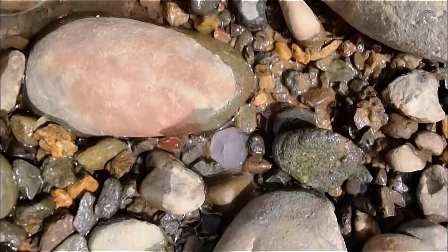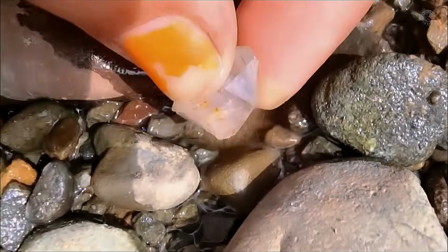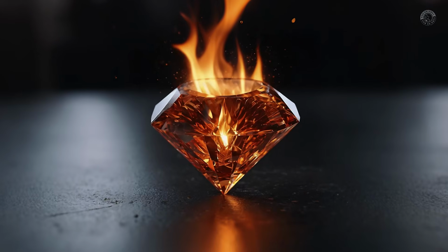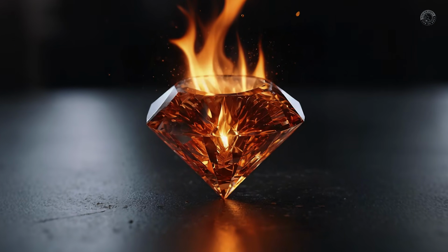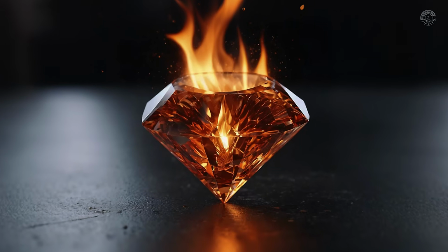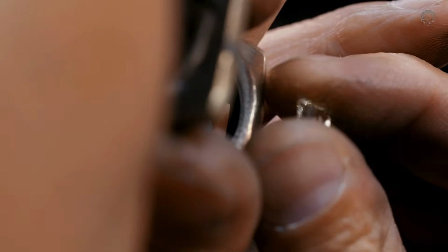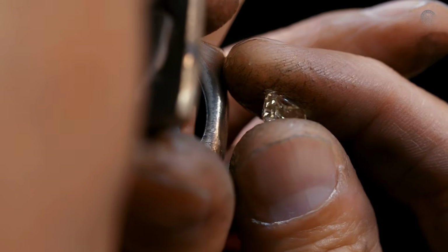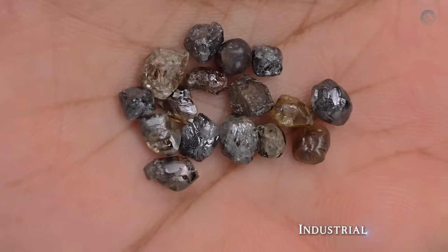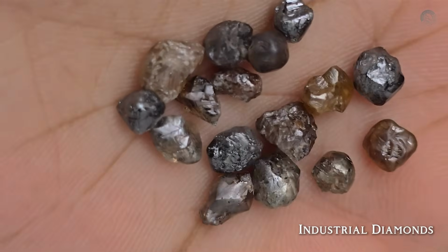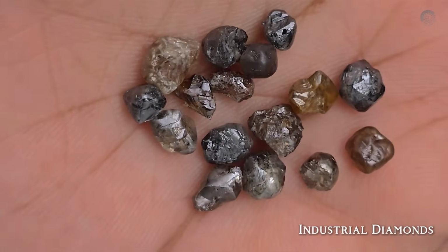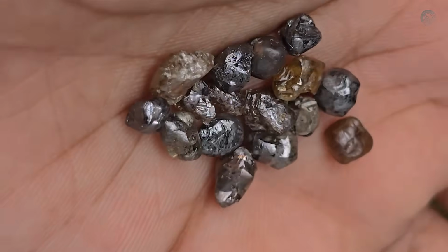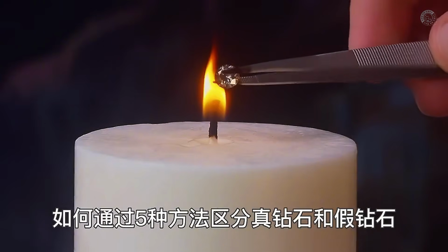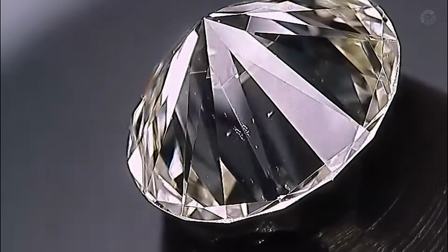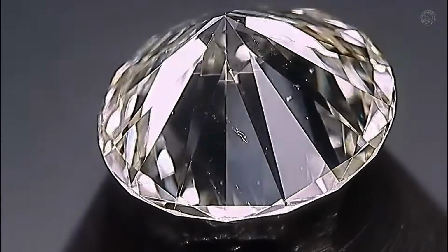But before jumping to conclusions, now that you've seen how glass, cubic zirconia, and quartz react so poorly to heat, it's time to focus on the real protagonist, the diamond itself. This is the moment when the difference becomes clear even to untrained eyes. Unlike simulants, diamond does not deform, develop internal fractures, or lose its brilliance when exposed to a direct flame for a few seconds. Its resistance comes from an extremely rigid crystal structure and its exceptionally high thermal conductivity. That means heat applied to one spot is quickly dispersed throughout the stone, preventing localized stress that could cause cracks. That's why, in a quick test with a lighter or a small torch, diamond stays unaltered. While imitations show obvious signs of thermal stress, diamond keeps its appearance as if nothing happened.